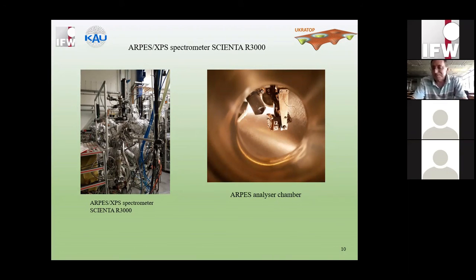The problem is that the gap in ARPES measurement was also not straightforward from the previous review. As you know, some gaps open apparently at very high temperatures, and then transport shows that this is much lower. So when it's combined with the process, if the film is superconducting, you will see them. But what you're saying, Sasha, is correct for monolayers. And monolayer transport is really very sophisticated. But if you have thick films, and that's what we do at the moment, then characterizing by transport should be straightforward.